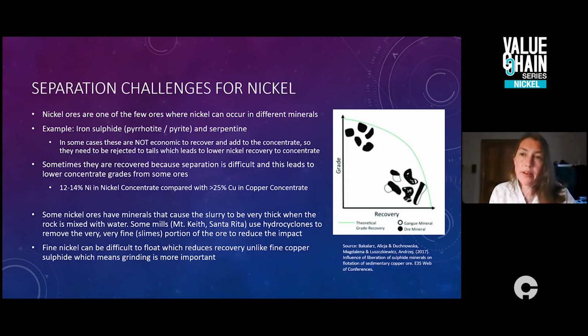Some challenges around nickel processing is that sometimes the silicate minerals, the waste minerals that are in the ore, can actually cause the slurry to be very thick. And you have to do some things to fix that and to make it amenable to a typical flotation process. Generally, a lot of places do that by adding more cyclones. We talked about cyclones and size separation. We would add more cyclones and take that very fine portion that causes that thickness, which we call the slimes, and remove those and send them to tails. And then once you do that, the remainder of the flotation is very standard. So there are some specific challenges related to nickel that aren't seen in some other base metal mills.